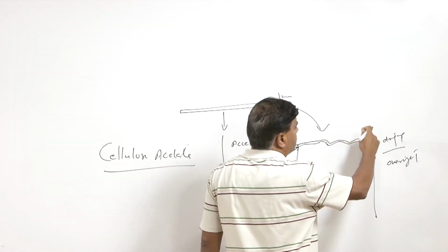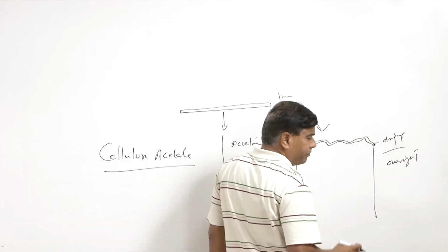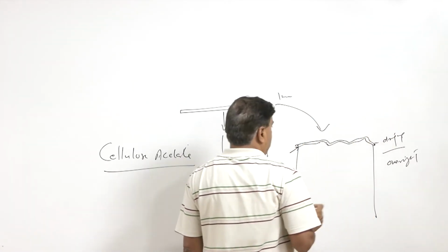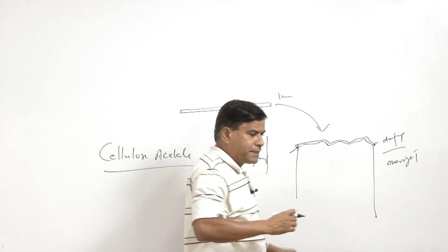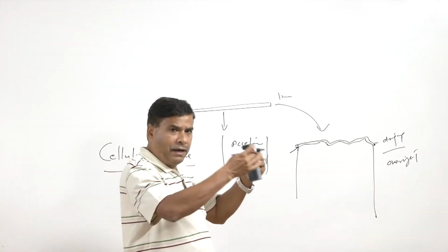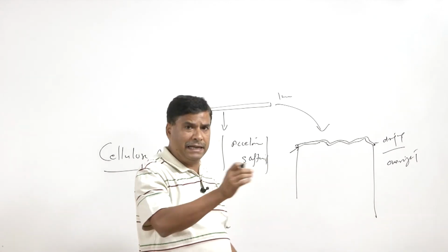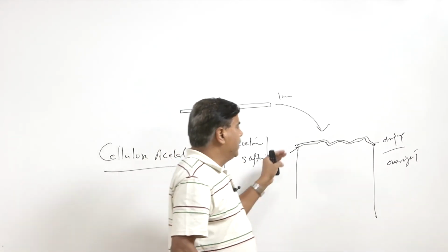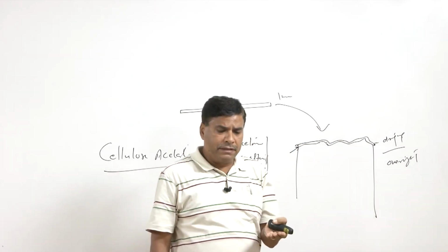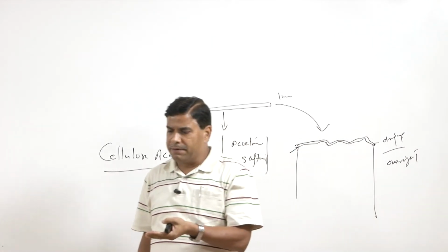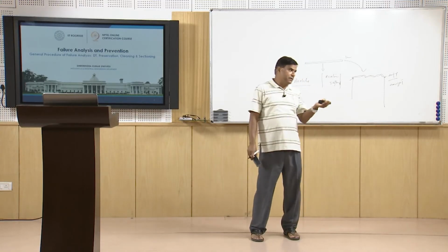Some of the impurities will remain attached to the sheet, and the same process is repeated until the sheet coming out after stripping is clean, which suggests that the surface has been cleaned. All those sheets are preserved, having the impurities and debris which were present on the surface of the fracture.